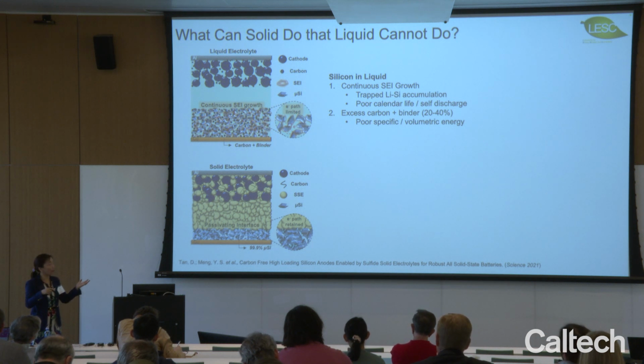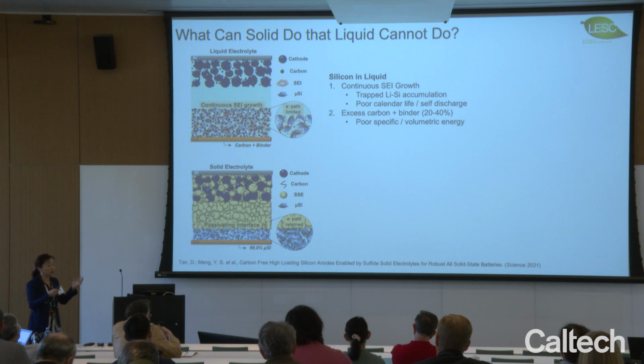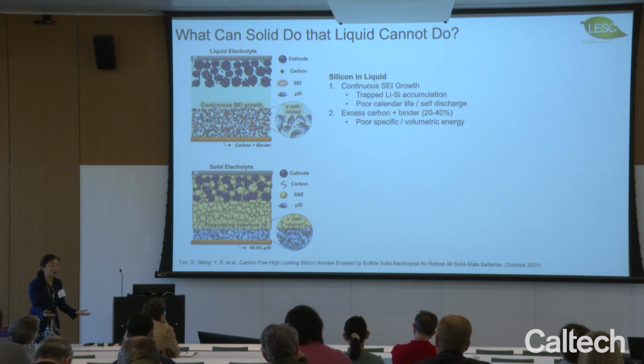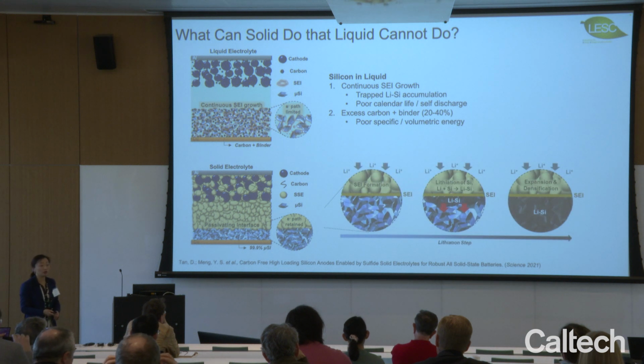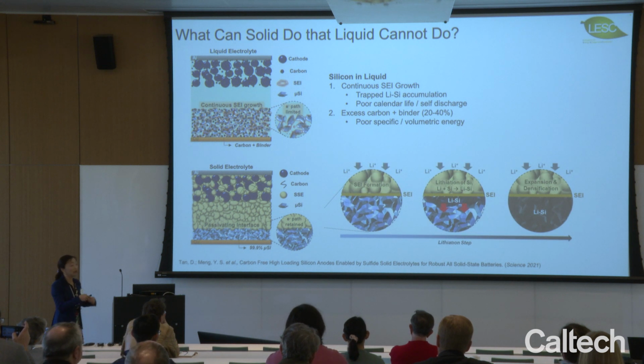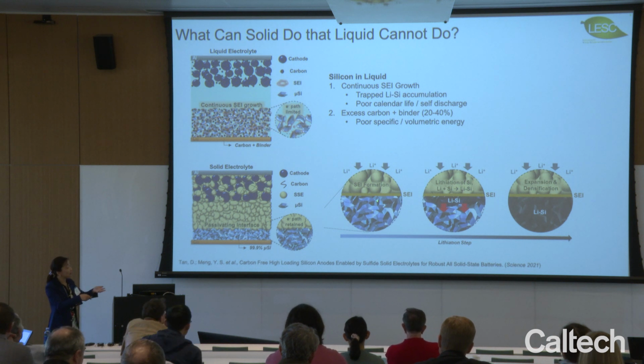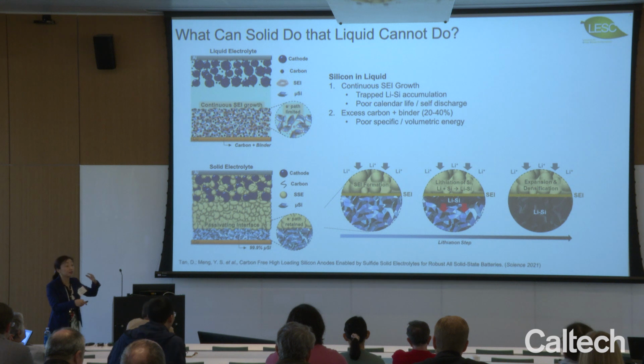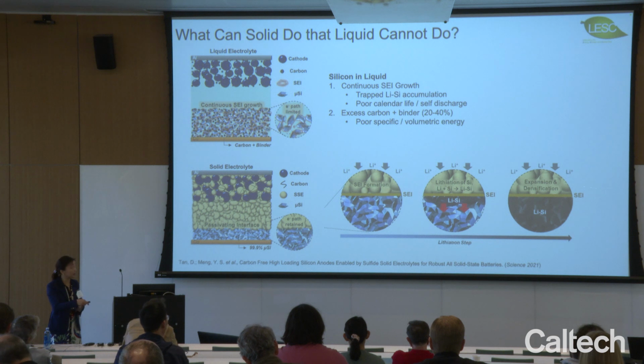So at first glance, this is an interesting thought experiment. The reason we do that is we think that even though gravity is there, the solid cannot flow. There is no flowability for the solid to go into the pores. So the hypothesis is that when you do the electrochemical process, all the lithium will be driven from the cathode to the anode under the electrical current, and this lithium silicon alloy should proceed without any interference from the electrolyte. So it is a complete solid-state alloying process driven by the electrochemistry process.